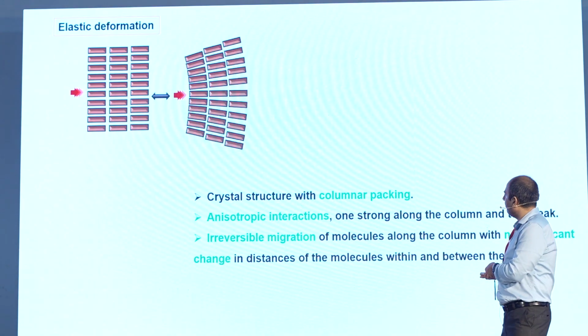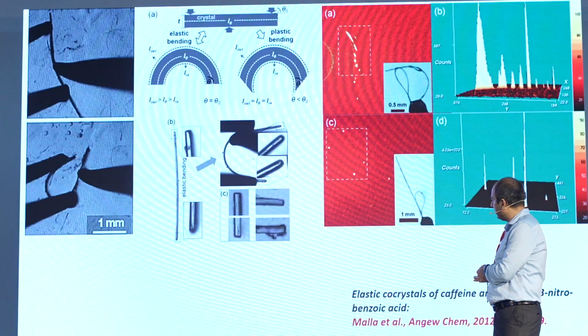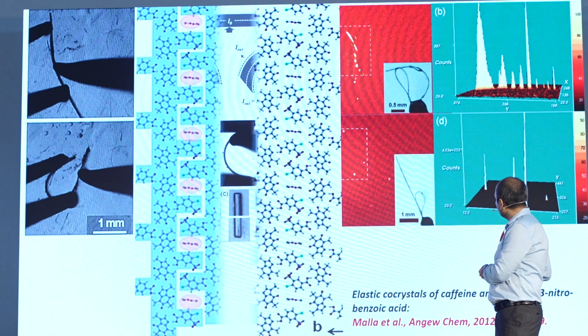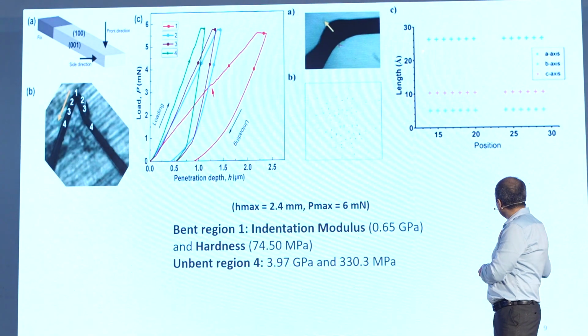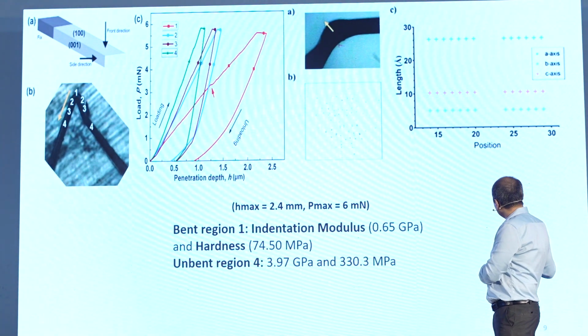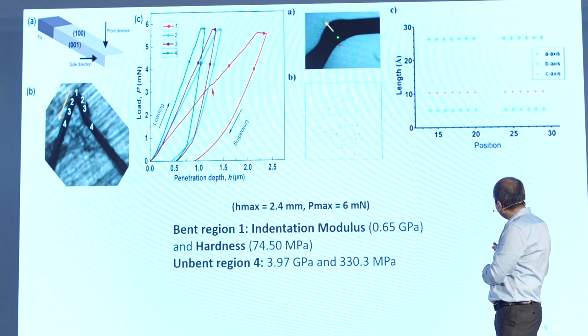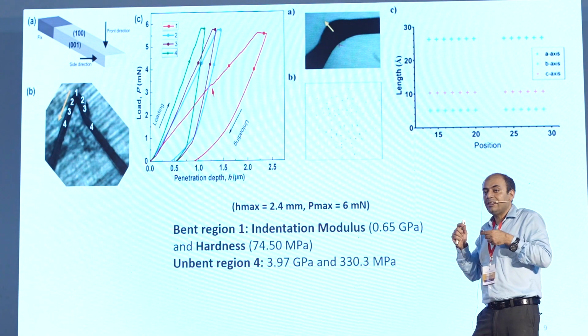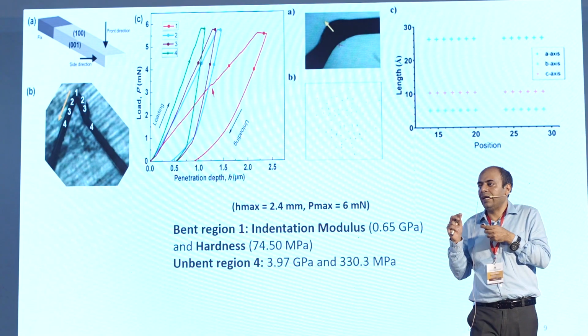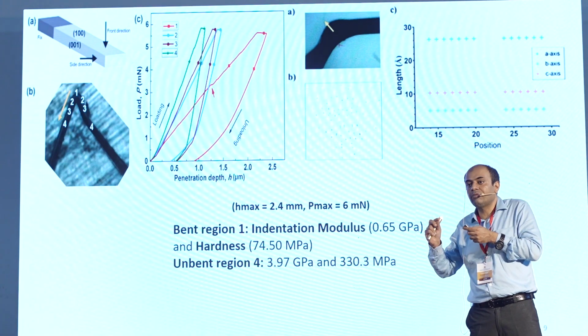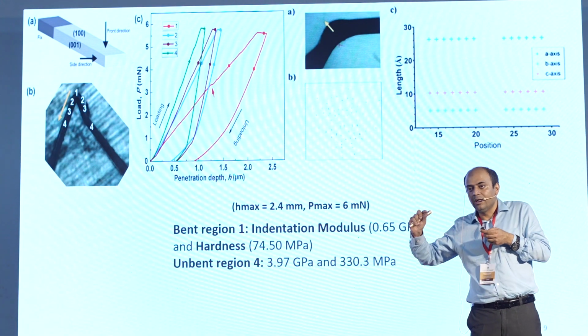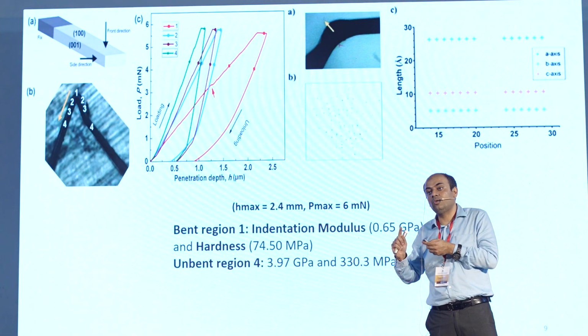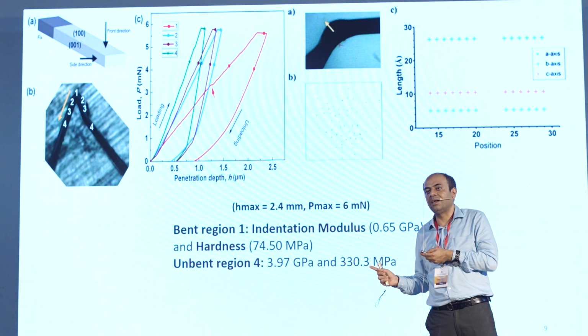No, these are all very high quality structure determinations. I'll tell you the difference. When you do these experiments, there are 30 experiments we did at different points. These structures are having loss of crystallinity. There is some mosaicity. So we are not able to refine the structures to a complete anisotropic thermal displacement parameter.